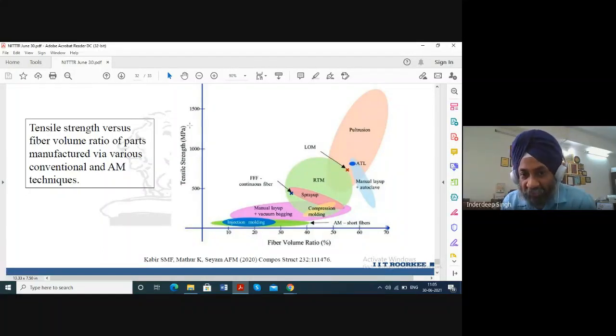So the tensile strength values that we can achieve are significantly lower, even lower than 500 megapascal for injection molding and the FDM process that we have used. But if we go for continuous fibers, the tensile strength can be significantly higher. Therefore, this shows that there can be a trend towards using continuous fibers in 3D filaments.